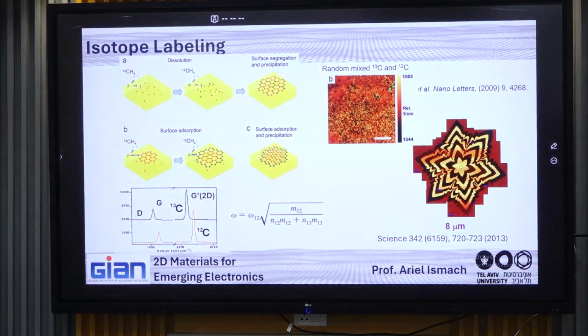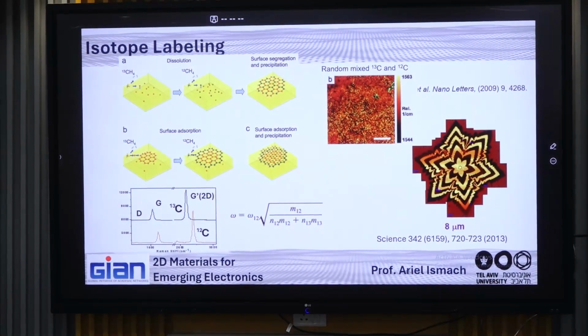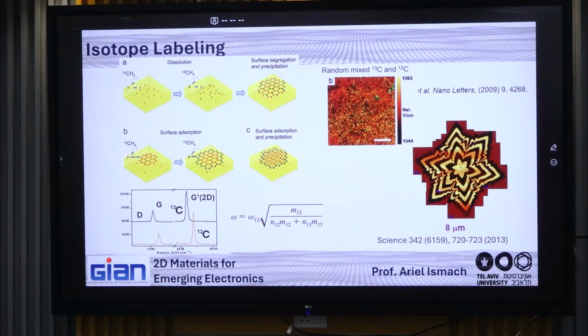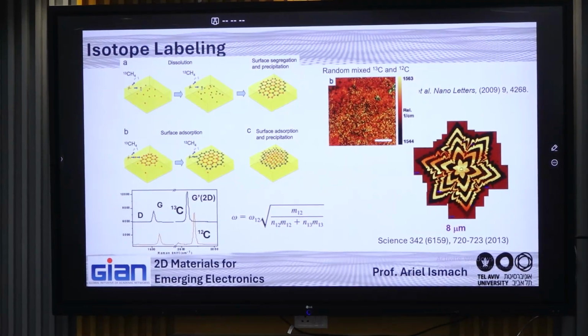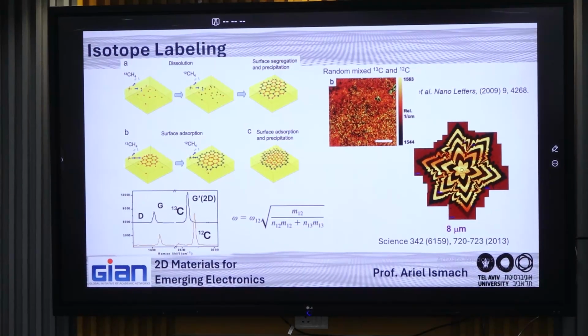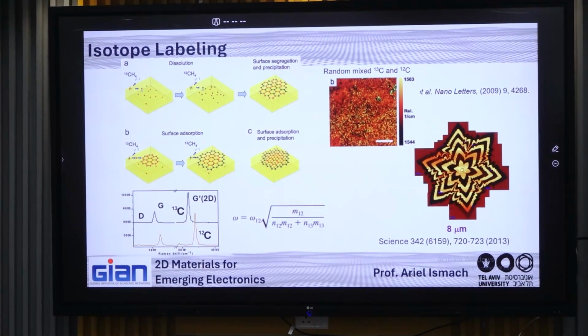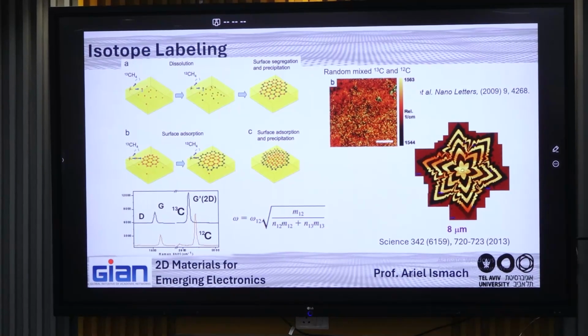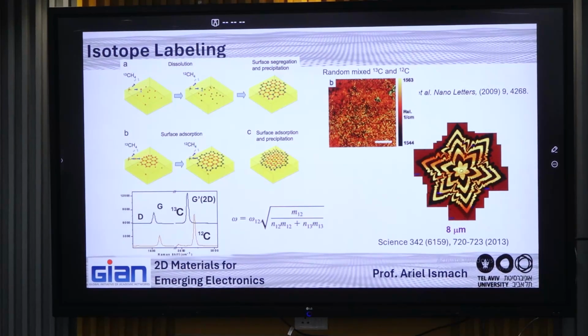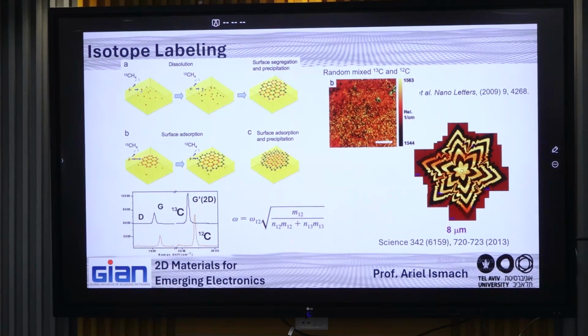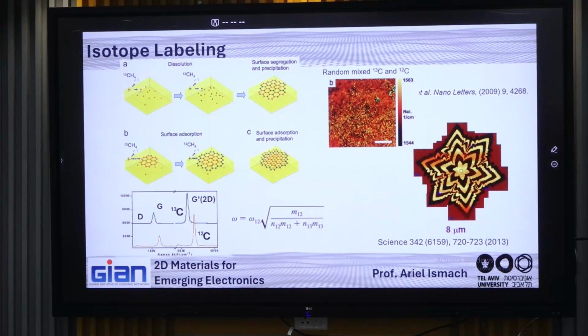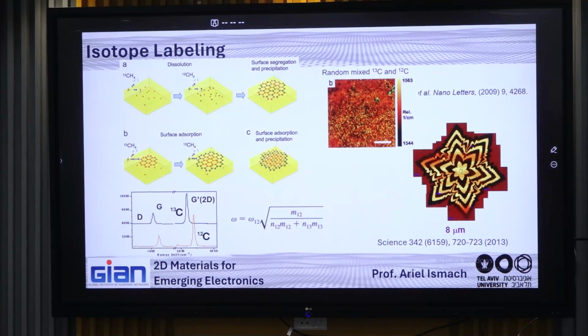But with Raman you can do more than that. As I told you yesterday, you can use it to study the growth mechanism, as was done for graphene on copper or nickel, right? Nickel: bulk diffusion and segregation; copper: surface mediated growth. You can basically elucidate the growth mechanism by an ex situ method, in this case, the Raman method. Okay? So you can use Raman for many other things, not only counting the number of layers and estimating if your sample is high quality.